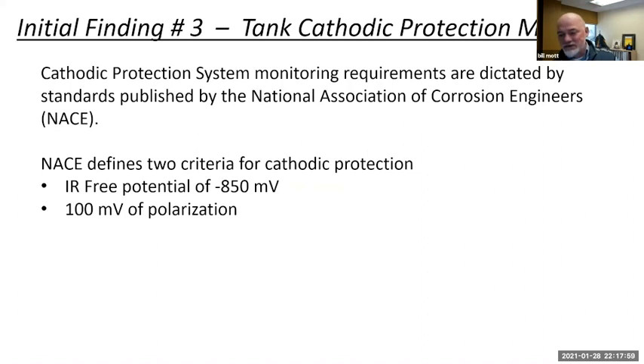These criteria were developed through testing, both empirical and laboratory testing. These are the conditions that are required to stop or dramatically slow corrosion on steel. According to NACE, the IR-free or instant-off potential can't really be more negative than 1100 to 1150 millivolts. So a good reading for a tank would be between 850 and say 1050 or 1100 millivolts. The 100 millivolt polarization requires that you measure the formation and decay of that polarization.